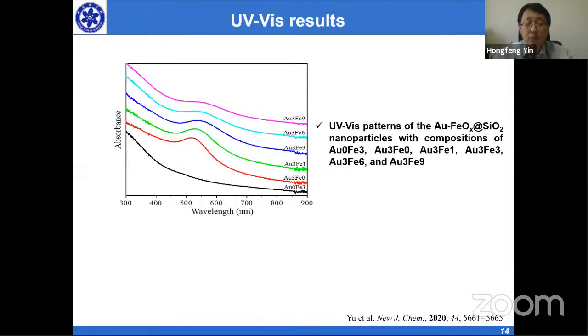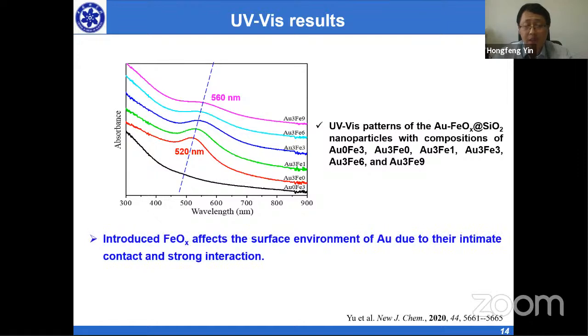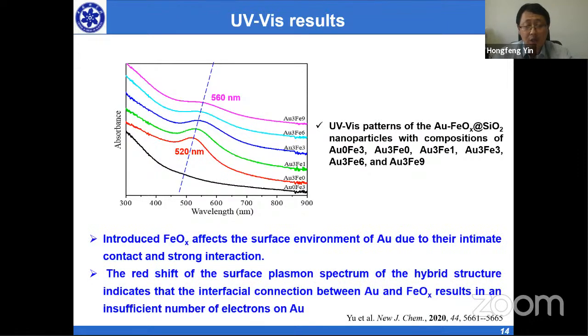We can see that even though no iron-gold alloy forms, the formation of the iron oxide gold composite will still make a red shift of the gold peak. So it will also make the gold electrons become insufficient.